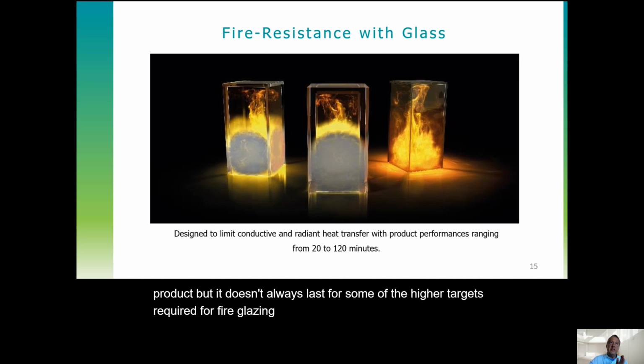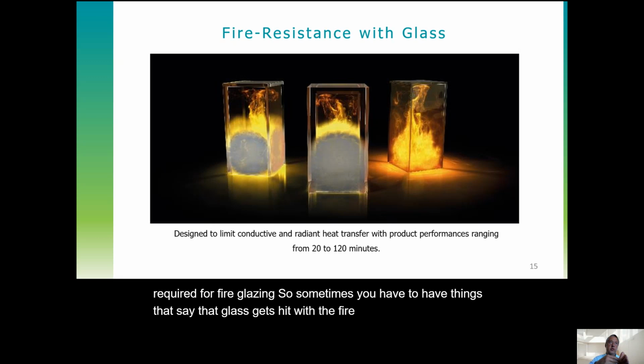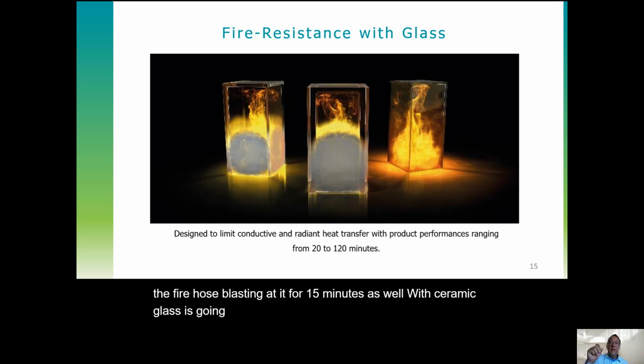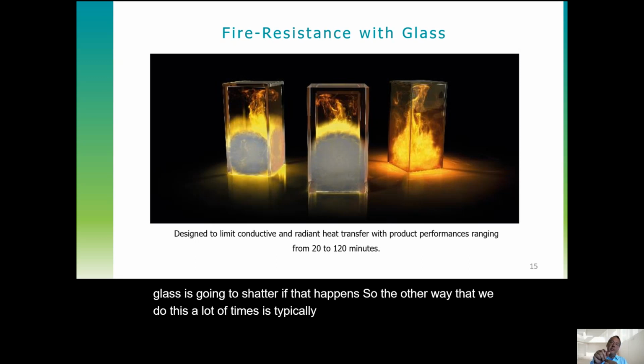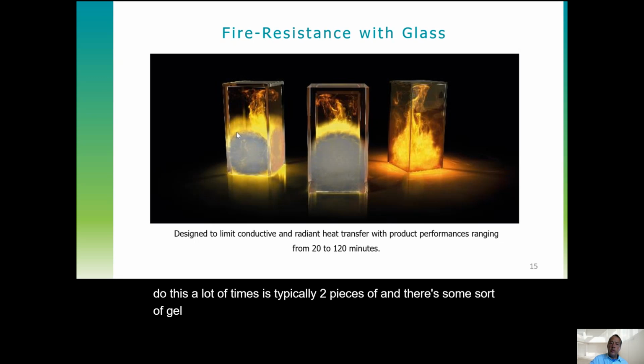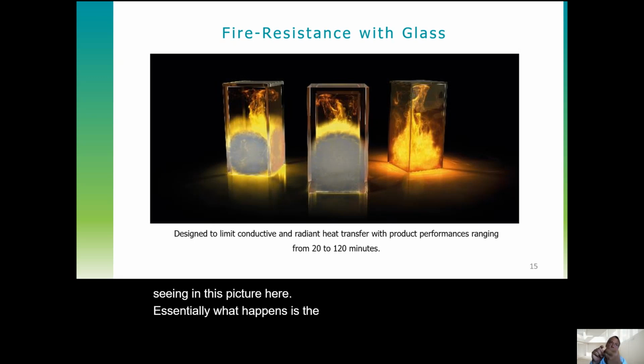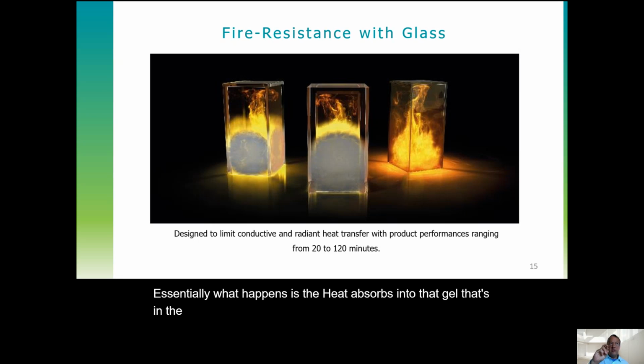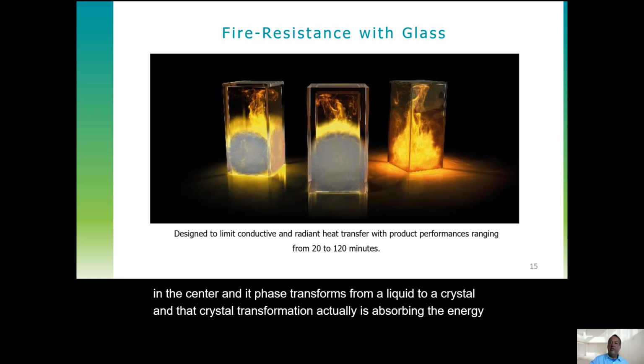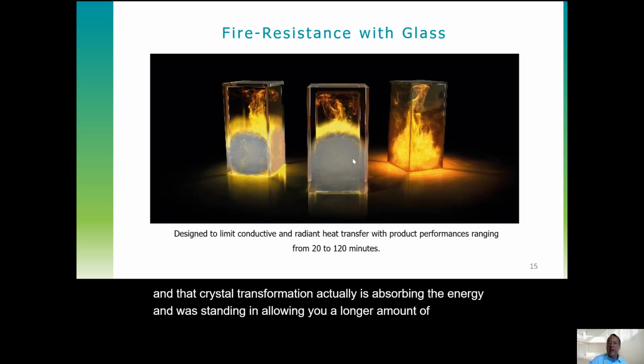Sometimes you have requirements that say if that glass gets hit with a fire hose, it has to withstand the fire hose blasting at it for 15 minutes as well. Well, ceramic glass is going to shatter if that happens. So the other way that we do this a lot of times is typically 2 pieces of glass with some sort of gel or goo in between them. That's what you're seeing in this picture here. Essentially, the heat absorbs into that gel in the center, and it phase transforms from a liquid to a crystal. That crystal transformation absorbs the energy and allows you a longer amount of time before that unit will fail.